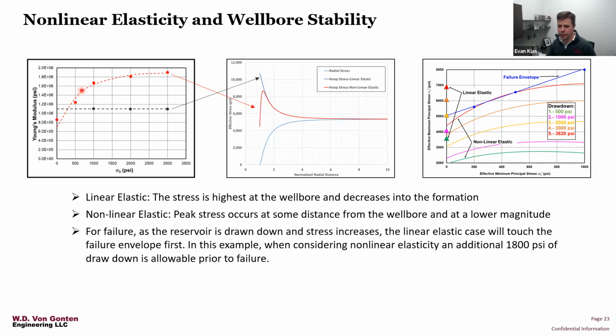This shows up in the stresses that manifest from these different models very differently. In the case of linear elasticity, we see a strong peak stress right at the wellbore surface, which usually results in what we understand as breakouts in the wellbore, and that stress declines moving away.